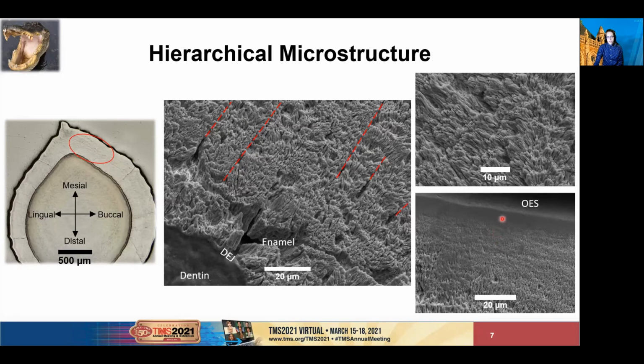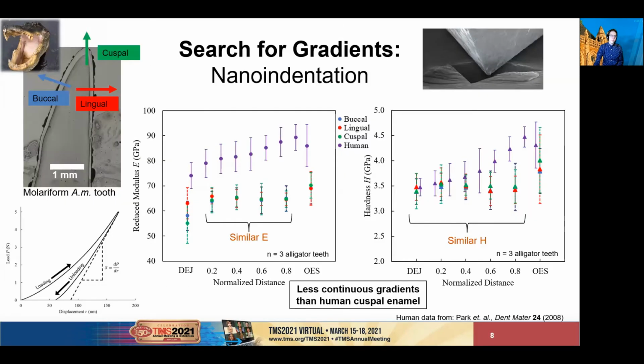When we see such an increase in the mineral density, you'd expect a change in the mechanical properties, which is what we investigated next via nanoindentation. Here are the average results of 3 American alligator teeth, all sectioned buccal lingually as shown in the micrograph. The force displacement curve of a representative indent is shown here, with a maximum force of 5 newtons and holding for 5 seconds before measuring the elastic response. We performed indents using an accelerated mapping feature, taking 9 measurements at each of 6 evenly spaced locations along a path through the enamel thickness, with the measurements at each end being within 10 microns either of the surface or DEJ.